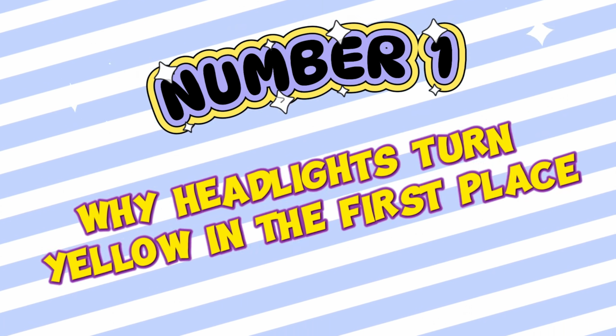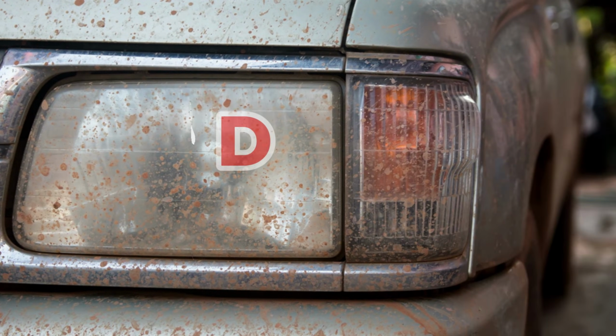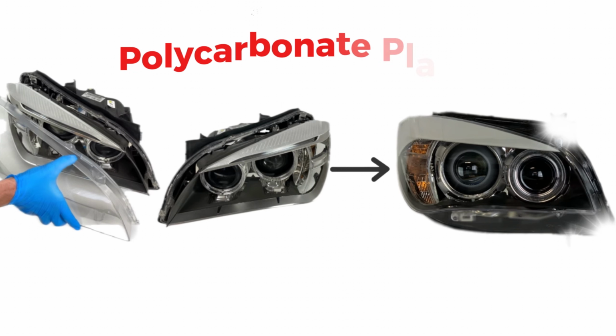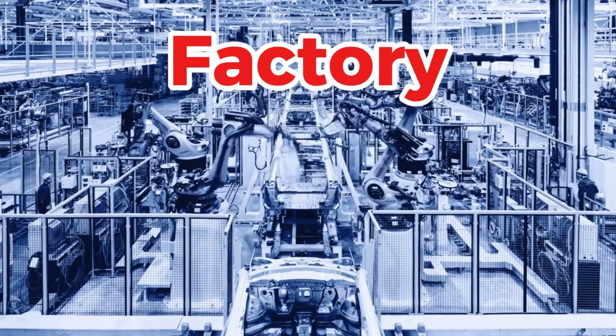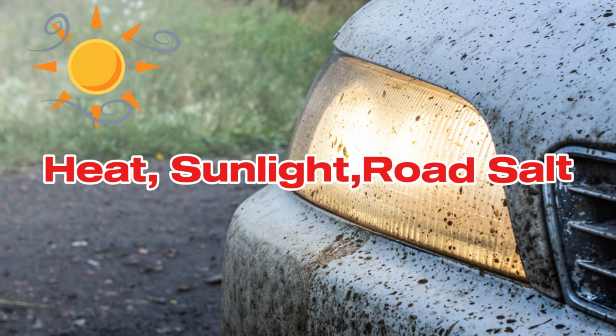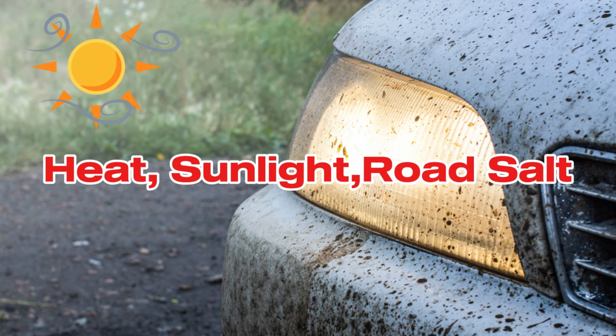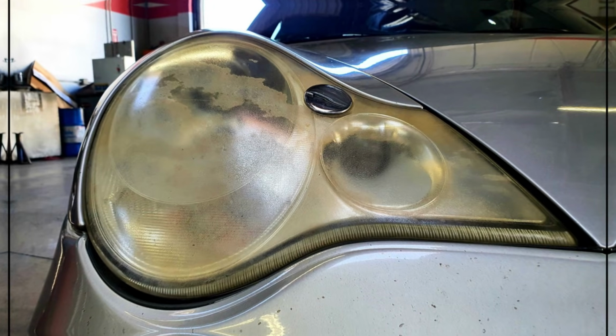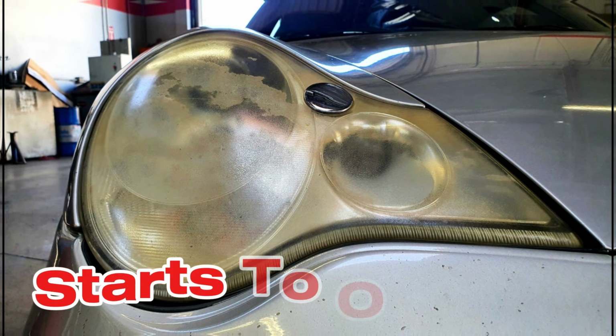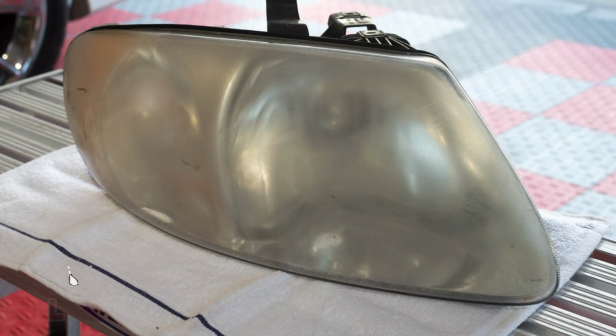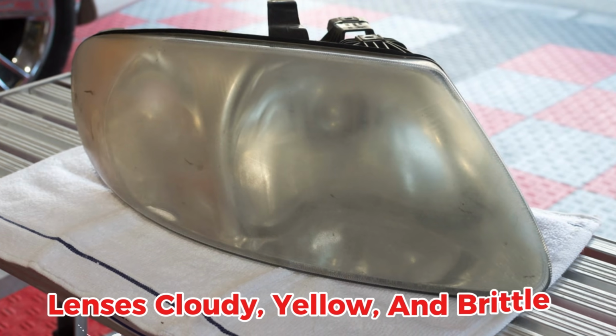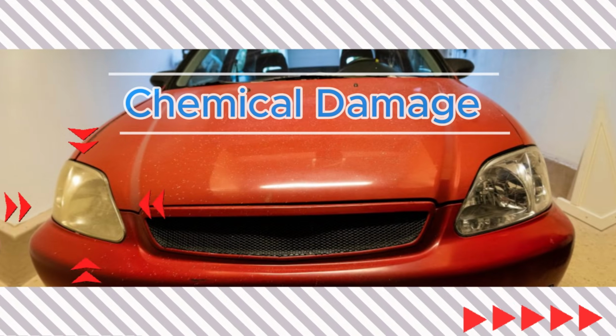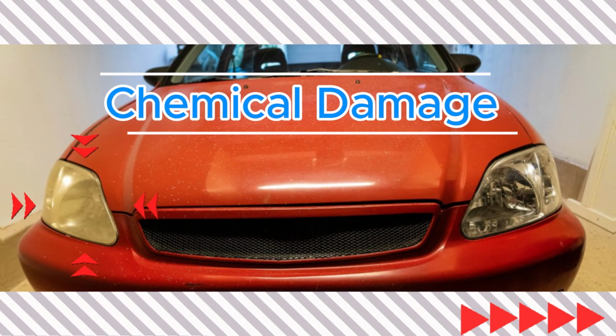Number 1. Why headlights turn yellow in the first place? Most drivers think headlights fade because they're dirty. That's not true. Headlight lenses are made from polycarbonate plastic, and from the factory they're coated with a thin UV protective layer. Over time, heat, sunlight, road salt, and pollution destroy that coating. Once it's gone, the bare plastic underneath starts to oxidize, and oxidation is what turns clear lenses cloudy, yellow, and brittle. It's not surface grime. It's chemical damage inside the plastic itself.